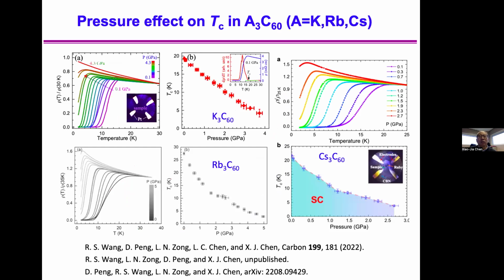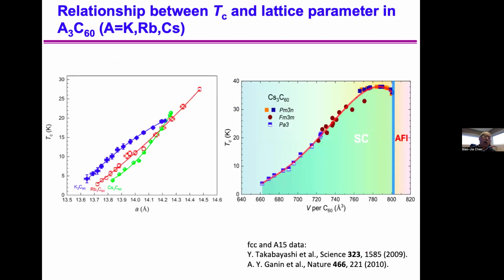We work in the field with carbon 60 doped with Rb or Cs, and we measure resistivity. We have the Tc measurement, and we also measure the structure with pressure. That's why we got the Tc changes with the lattice parameter. You can see in the three systems of carbon 60, K3, Rb3, Cs3, if we put them together, we get the figure in the red panel.